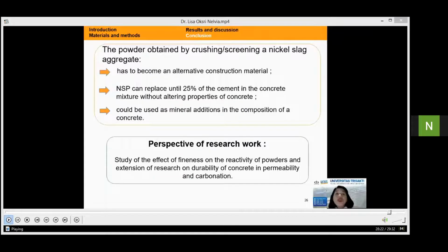We can just draw three conclusions at the current state of our research. Firstly, NSP can be used as a substitution for Portland cement in the concrete mixture, and it is expected to become a green alternative construction material. Secondly, in general, the results reveal that NSP can replace up to 25% of the cement in concrete without altering properties of concrete. And lastly, it can be used as a mineral addition in the composition of a concrete with a substitution rate of powder equal to 25%.